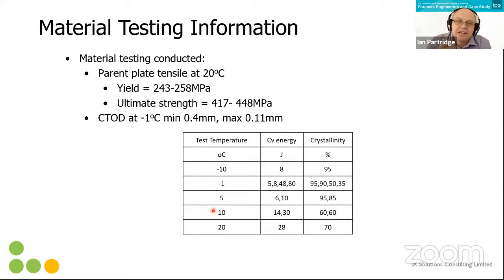The material testing showed that at 20 degrees C you were getting quite high, reasonable Charpy energies. Then as the temperature dropped, it was significant. Even at 5 degrees, they were getting values of 6 joules. For those of you who don't get involved in this, normally you want 27 joules at your minimum temperature. So these are well below what was expected.